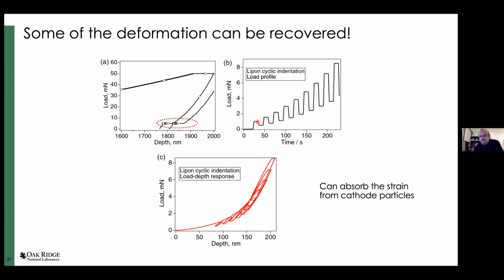You indent it to the peak load, then you unload it to 1/2, and then go higher and unload to 1/2, and so on and so on. At each segment, you hold it for some time and you observe the deformation, and this is again the bizarre behavior. You see this almost hysteresis loop where, at each unload and cycle, LIPON restores its deformation. So potentially what it tells us is that it could work very, very nicely as a barrier buffer material between the cathode particles because it almost can breathe with the particles back and forth.